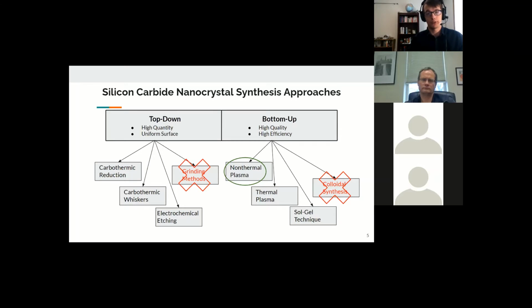Another top-down approach is based on electrochemical etching of bulk silicon carbide. In this technique, a wafer of silicon carbide is placed in a reservoir of the etchant, which is usually hydrofluoric acid with another solvent such as ethanol, and that's under a current flow. This creates a porous silicon carbide matrix in the wafer through which the individual nanocrystals can be liberated by sonication in a bath. This method is nice because the end product is predictable, because the structure of the silicon carbide nanocrystals will always take the same form as the parent wafer. So if you start with a hexagonal parent wafer, then you'll end up with hexagonally formed silicon carbide nanocrystals.